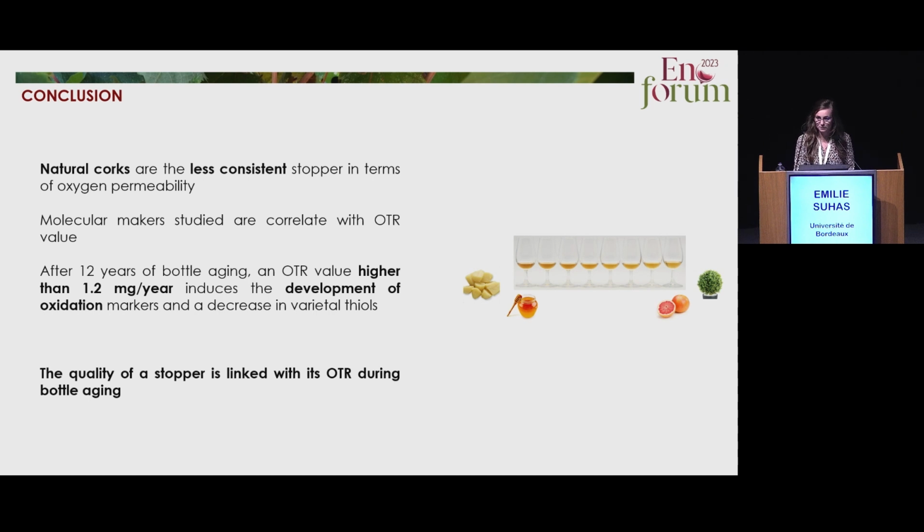So, in general, to summarize the results that I have illustrated today, we have several different pieces of information that one needs to remember. The closures, the stoppers made of natural cork, regardless of the quality, display a very high level of variability between similar corks.